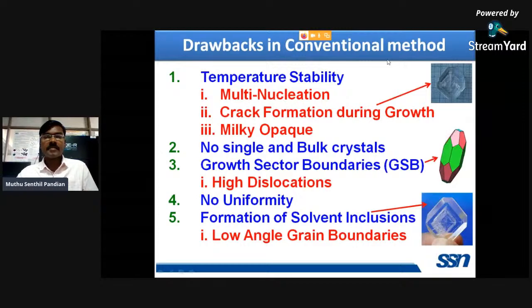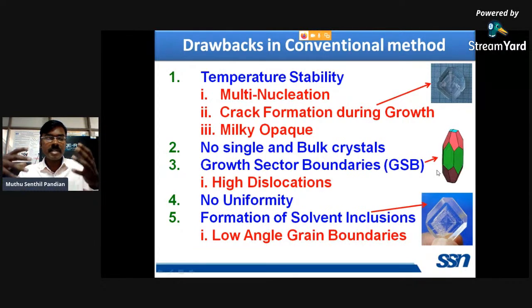So the drawbacks in the conventional slow evaporation method: due to temperature instability, multinucleations are formed in the growth chamber, and cracks form during growth. If you see all the conventional method grown crystals, you can easily see micro cracks appeared in the grown crystals due to the temperature instability of the growth chamber. And milky opaque regions are also formed in the conventional method grown crystals. So we cannot grow bulk size single crystals because of the restricted availability of the material ingredients in the conventional method.